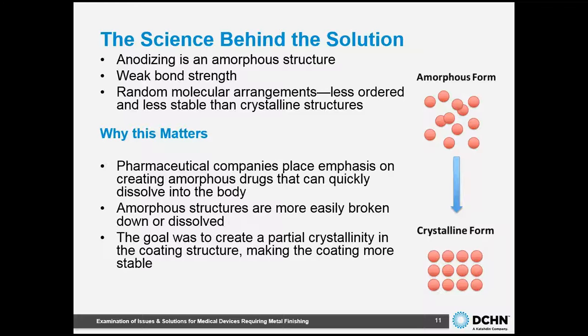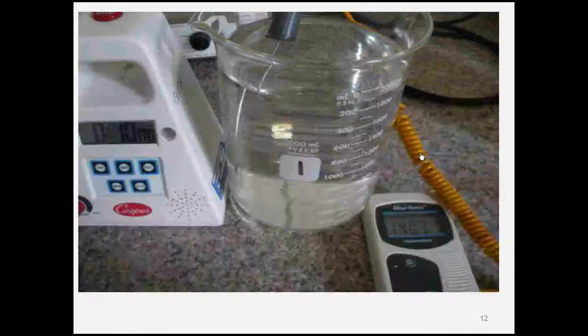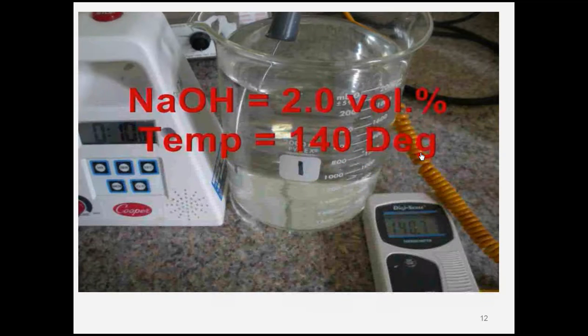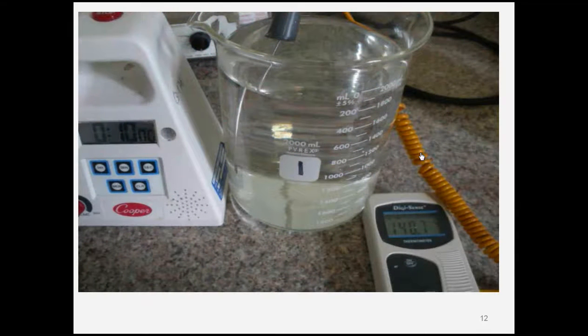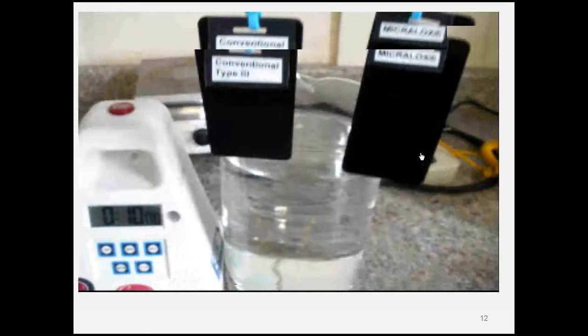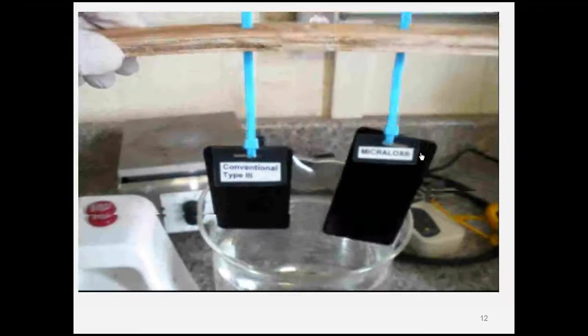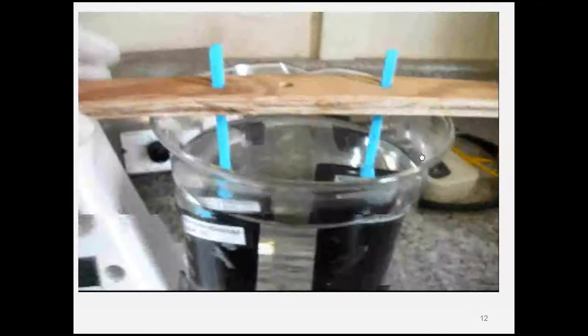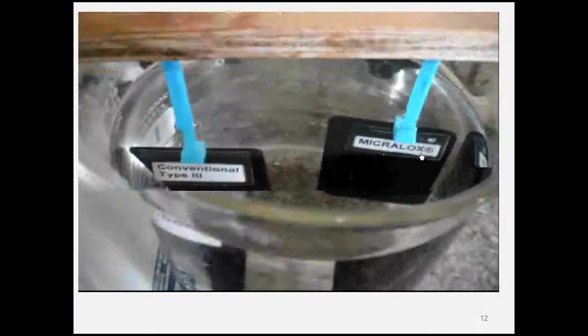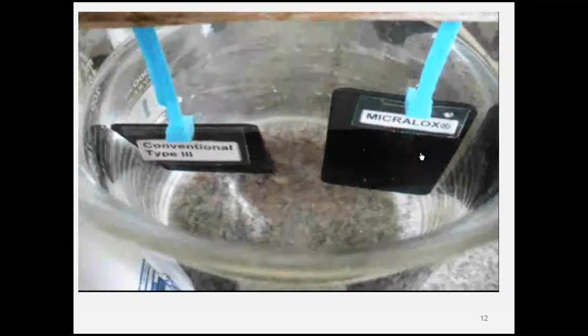Let me explain further why. We'll watch a clip of a traditional amorphous hard coat anodized and a partially crystalline anodic hard coat in the presence of a very high pH solution of sodium hydroxide. Bear with me. Okay, so let's talk about what we're going to see here. We have a solution of sodium hydroxide at 140 degrees, which is a common solution for anodized companies to strip anodic coatings from racks or from parts that are rejected in their plant, or when people take it back from the field.